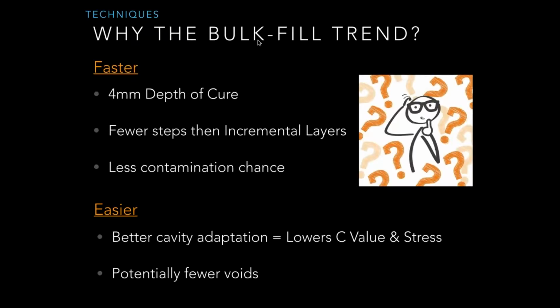Why the bulk fill trend? Besides reducing the restoration time, bulk fill materials possess a self-leveling effect and adapt nicely to cover all the surfaces, lessening any chance of voids. This in turn reduces the postoperative sensitivity. Essentially, bulk fills have become the dentin replacement in a single increment. They are placed in 4 to 5 millimeter increments and light cured adequately for 20 seconds.